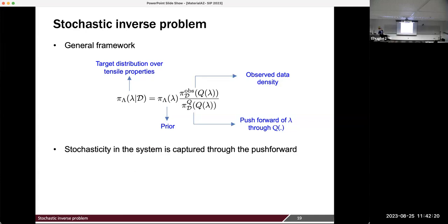Questions? Yes. So with the elasticity, when you're actually measuring it, you're pulling it, right? What are you measuring and how, with the force push? So you basically take an indenter and make indents on the surface. It's not exactly like pulling, but it does create that response when the material is deforming, so you're able to measure how it is deforming with the force. At least so far, it has been very hard to completely replace tensile measurements. But if we generate more confidence that we can accurately estimate not just the mean values, but also the distributions, then we can do it.